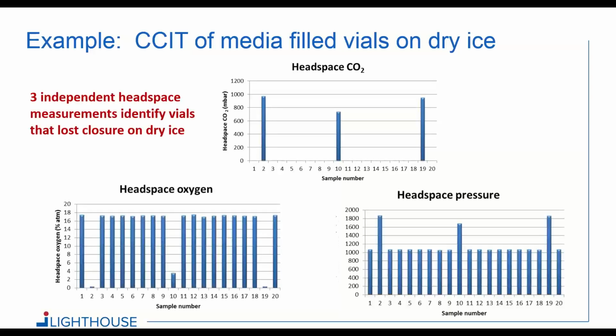You can also detect this with other headspace measurements. On the bottom left, if you look at the headspace oxygen, it's no longer around 20%. The same 3 vials show depleted oxygen levels, which correspond to the CO2 gas displacing the air inside the vial. And then finally on the right, this overpressure phenomenon, you can also measure headspace pressure per vial, and you see that the same 3 vials are measuring an overpressure. These are all non-destructive measurements. 3 independent headspace measurements identified vials that had closure issues during the dry ice storage.